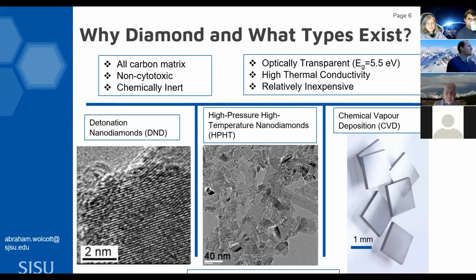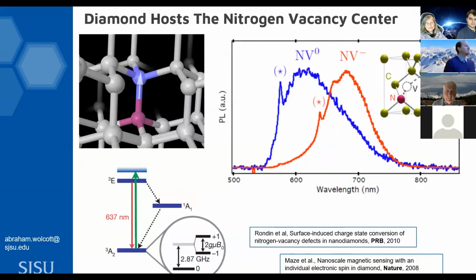Now, with our NV centers, which are hosted within the diamond, and of course we can go back to that sun-drop diamond, we know a couple of different things because of the fundamental work on NV centers. We know they can readily absorb visible light, typically 532 nanometer laser light. And we realize that the extra electron, when it's sitting inside of the NV center, creates this ground state triplet. Now, the ground state triplet has these unique properties, which are summarized in the electronic configuration energy level diagram in the bottom left.